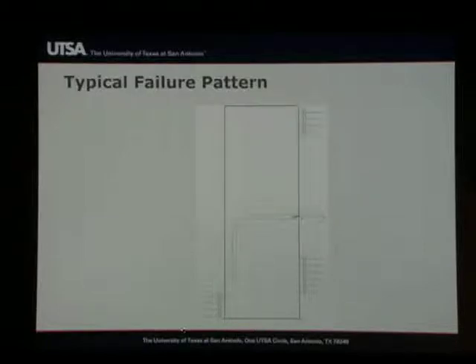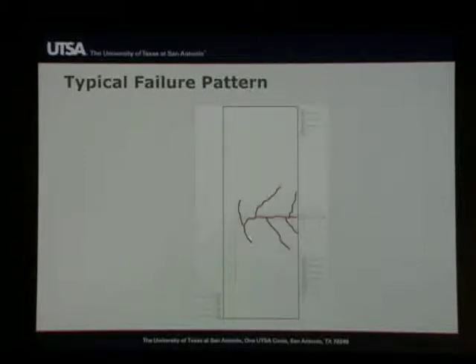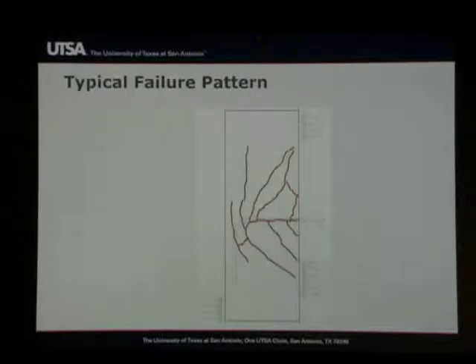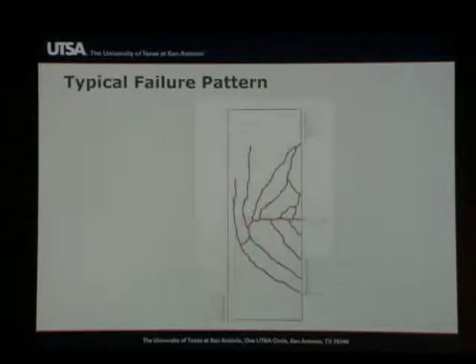This slide shows a typical failure pattern. You start to develop cracks along the length of the bar, and then those bars tend to go towards the back of the hook. And once you get towards the back of the hook, then you see those cracks start to follow the orientation of the struts towards the two supports. And then finally, you would develop what amounts to kind of a pull-out cone.